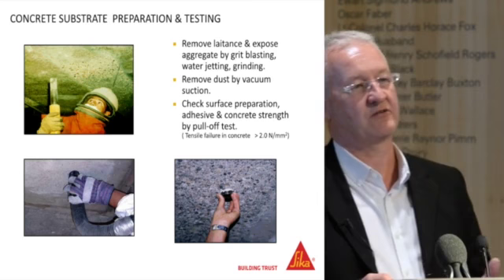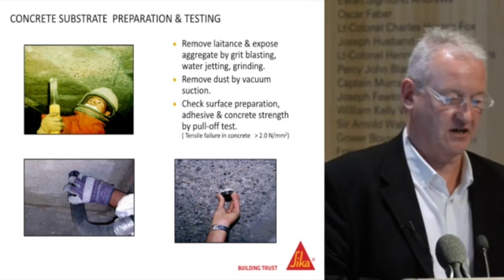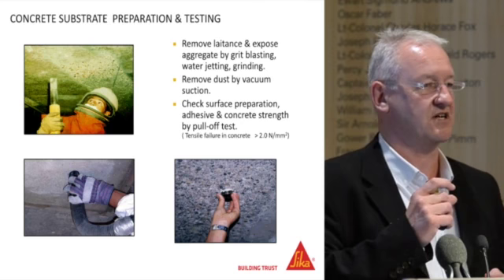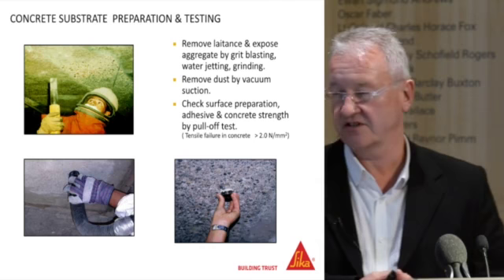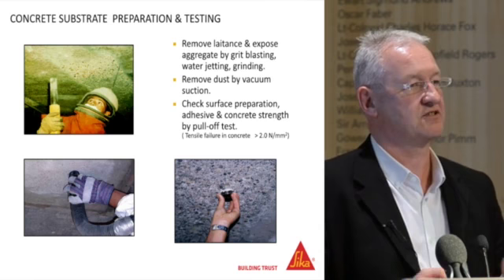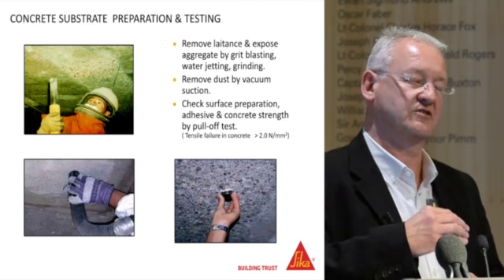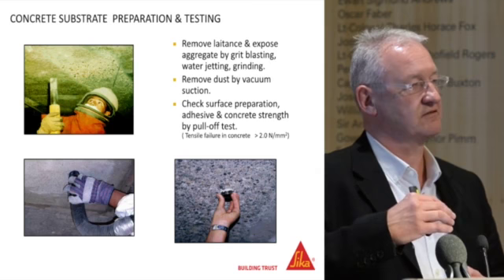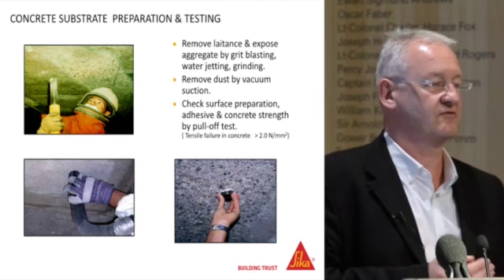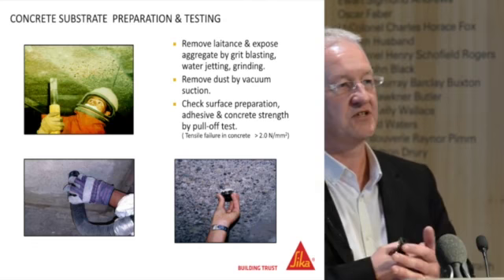After surface preparation, any dust or deposits must be vacuumed from the surface. To check the concrete surface has been prepared correctly, a pull-off test is performed — a steel dolly with adhesive is attached to the surface, left to cure, then pulled off. You should get a value of around 2 N/mm² minimum. What you're ultimately looking for is a conical failure in the concrete. You don't want adhesive failure at the dolly interface, failure in the protective coating, or cohesive failure in the adhesive. If you don't get concrete failure, you may need additional surface preparation, as polished aggregates require a coarser profile.